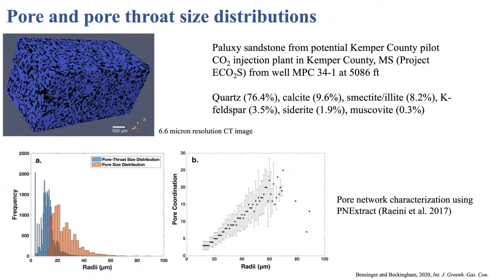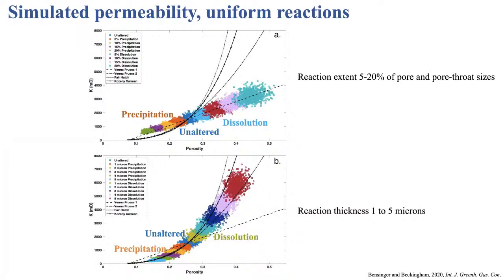So here we're going to use the same sample that we talked about for reactive transport from the Paluxy Formation. We took some CT images of the sample and got information on their pore network structure from PN extract. So we can get pore and throat size distributions as well as connectivity. And then carried out a series of pore network modeling simulations. So here we have the simulation results for uniform reactions. We have a variety of sub-scenarios, which is each of these different colors. And for each sub-scenario, we carried out 1,000 pore network models and then have plotted the results.